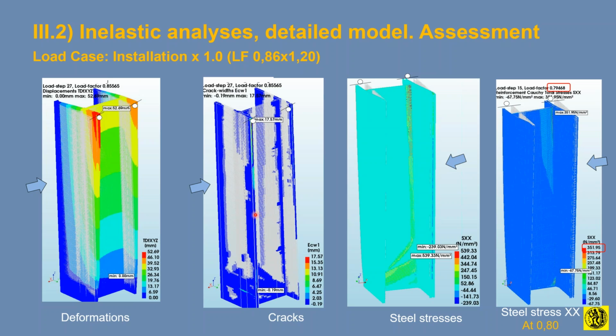This crack actually continues in the midspan of the chamber, and already we develop 45-degree cracks of the cantilever as a beam, actually. So the full cantilever truss analog, if you like, develops in this particular I section with an effective stiffness here, an effective compression side, and a tension side. So actually, the cracked model is much closer to the distribution of forces we should expect, the tensile demands of this specific area, as opposed to the linear elastic predictions of the sandwich model.